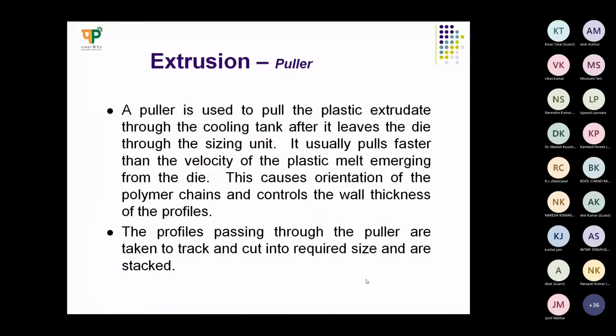Then it will finally go to the puller. A puller is used to pull the extruded plastic through the cooling tank after it leaves the die through the sizing unit. It usually pulls faster than the velocity of the plastic melt emerging from the die. So this causes orientation of the polymer chains and controls the wall thickness of the profiles. The profiles passing through the puller are taken to the track, cut into the required size and stacked.